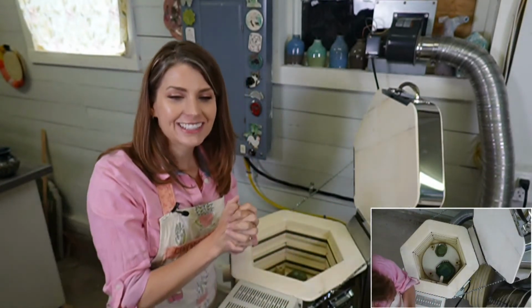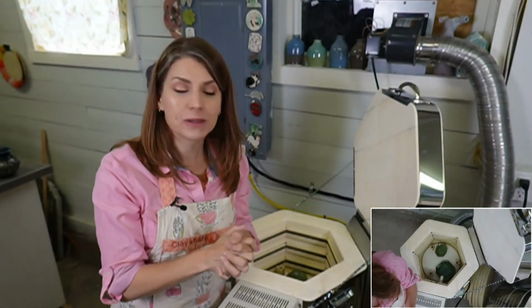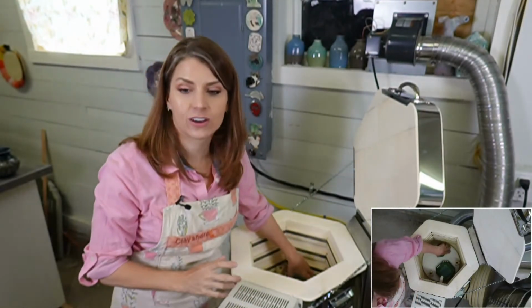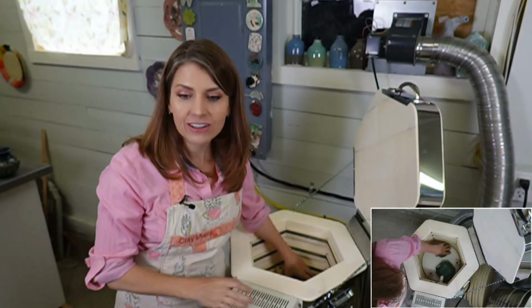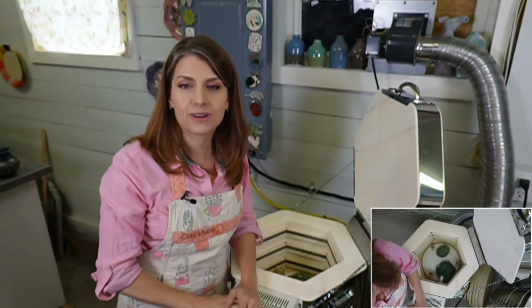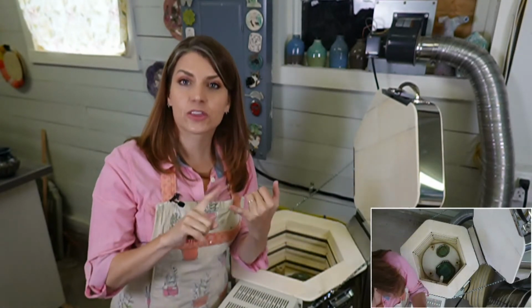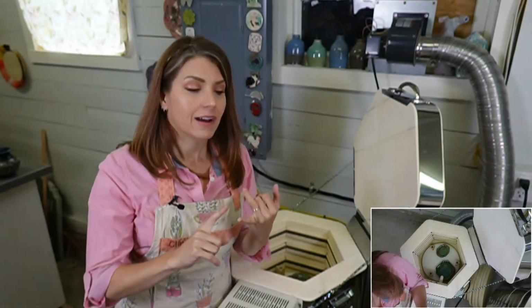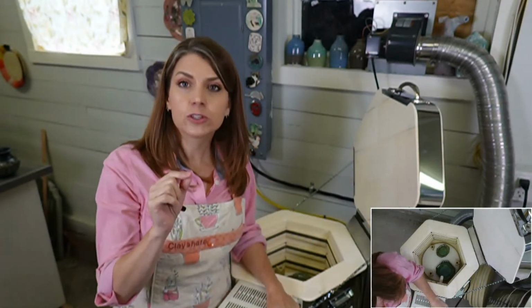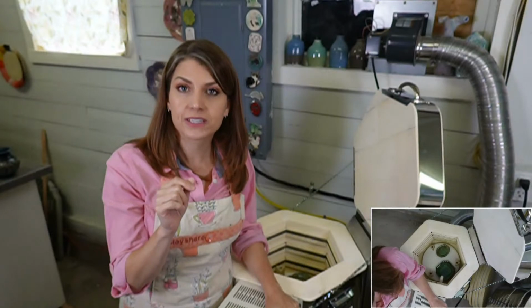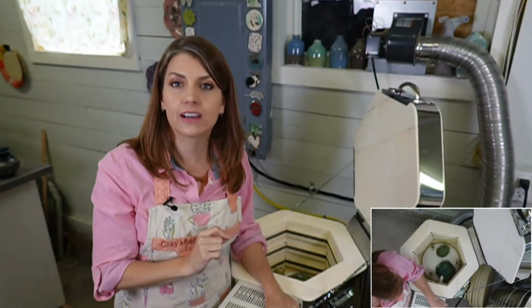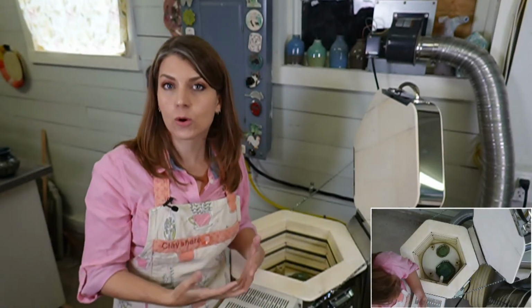All right, so Marianne says she just ordered a whole bunch of all the new Speedball underglazes. You're going to love them. They're gorgeous. So how long do I preheat for a bisque? Janet wants to know. 3 hours. My bisque is a 3-hour preheat for normal pieces. If I'm doing thick pieces or sculptural pieces, I'll do a 6 to 8 hour preheat on a bisque. So it depends what you have going in the kiln.